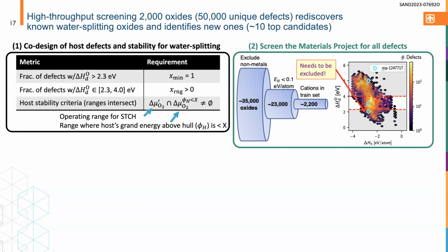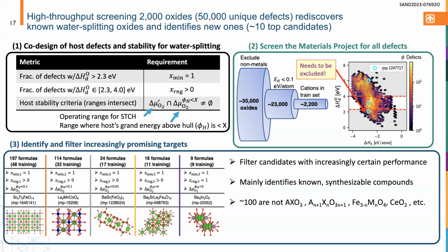This is just showing the general correlation that everyone knows about who works in this field, that the defect formation energy is in general correlated with the formation energy of the host crystal structure, but that's far from perfect. You certainly need to be able to predict each defect in the material, because I'm just showing in the blue there one material where there's a huge range of oxygen vacancy formation energies, and you would need to toss that material out of your down selection. Next.